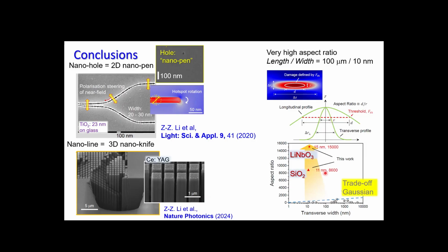But in this nanoscale material modification with the Bessel beam, the modification is actually happening because of light scattering and dipolar interaction along the propagation. So aspect ratios up to tens of thousands can be reached. So it's certainly Bessel beam fabrication. It's not fair to compare with a Gaussian beam, but somehow those numbers are very, very high.